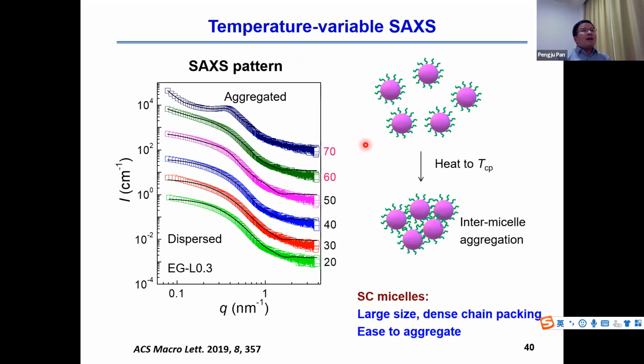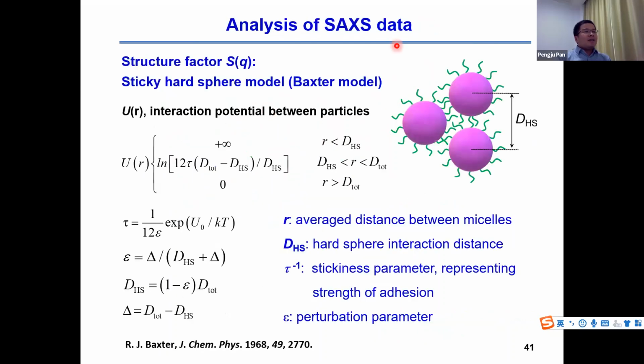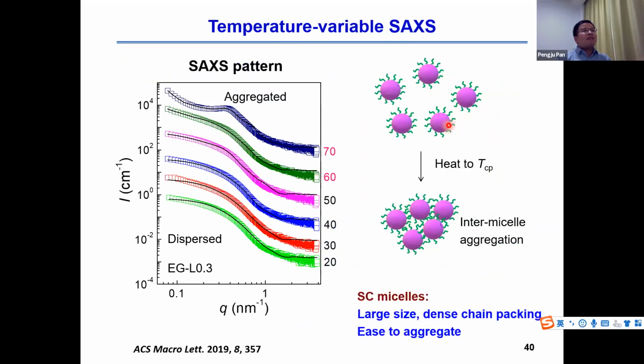We further use the temperature variable SAXS to analyze the thermo-responsive mechanism of the copolymer micelle in solution. When the temperature is above the cloud point, we can see a correlation peak in the SAXS curve. This peak is related to the interaction between micelle particles. We use the sticky hard sphere model as a structure factor to analyze the distance and interaction strengths between the micelle particles. We found the intermicelle attraction force increased after the stereocomplex crystallization.